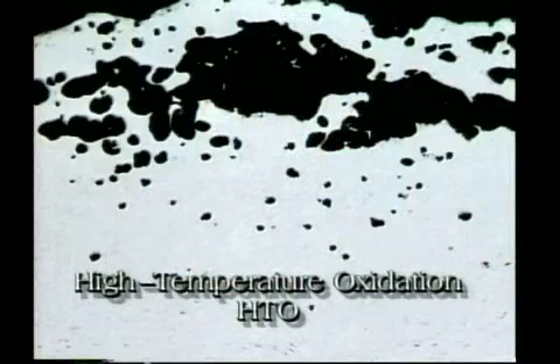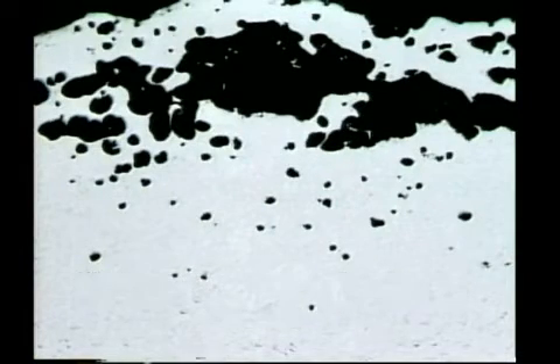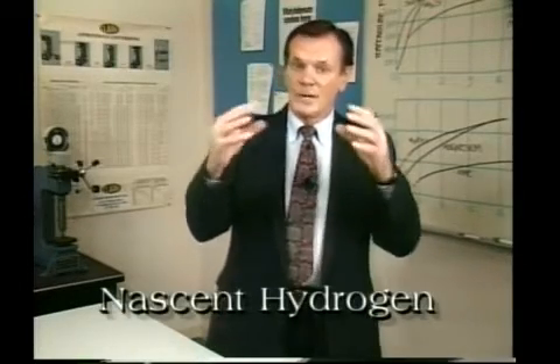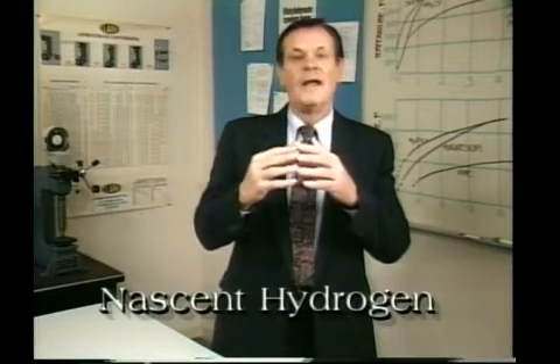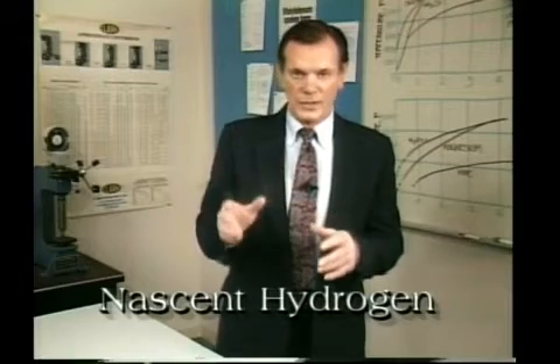Blisters are part of a phenomenon of aluminum alloys that is erroneously termed high-temperature oxidation, or more commonly HTO. High-temperature oxidation is evidenced by the formation of small rounded voids or crevices within the metal and by surface blisters. The reaction that causes the blister is not an oxidation reaction, but rather the reaction of moisture or some other hydrogen-producing material with the aluminum surface at the solution heat treating temperature. This reaction produces atomic or nascent hydrogen, which then diffuses into the aluminum lattice. The atomic hydrogen then recombines to form molecular or gaseous hydrogen at discontinuities, such as grain boundaries or voids in the structure.